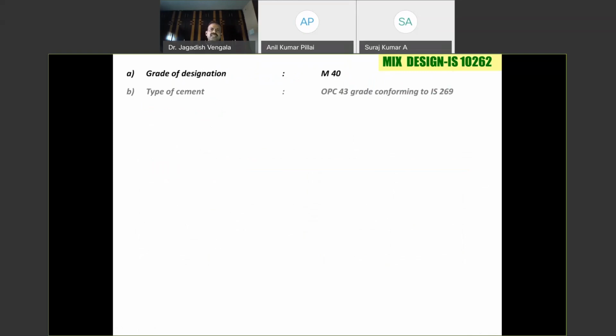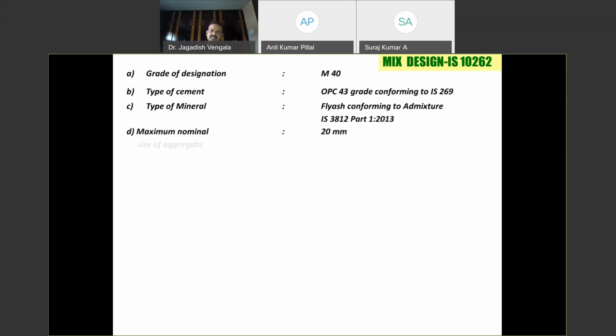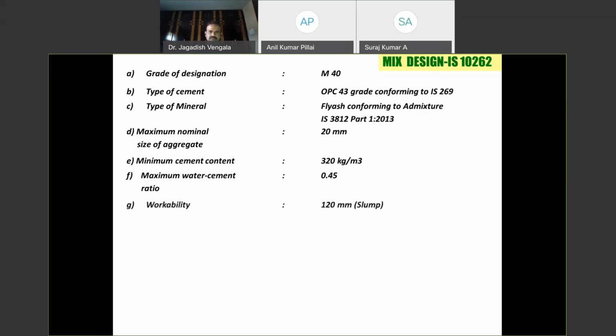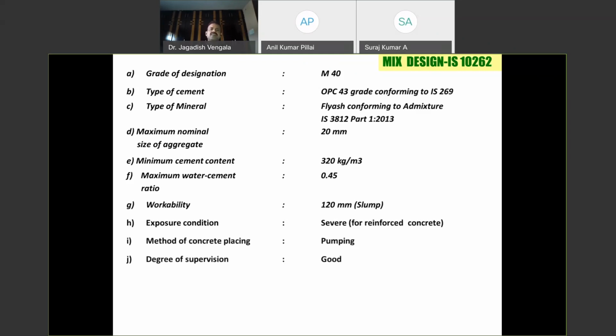So these are the details. M40 is taken, OPC 43 grade, which conforms to IS 269. Fly ash is taken as a mineral admixture, 20 mm. And these are the stipulated minimum cement requirements. The maximum water cement ratio is 0.45 because the condition is severe exposure condition. The workability requirement is 120 mm slump, and you have to pump the concrete. The degree of supervision is good, and the aggregate is crushed angular.